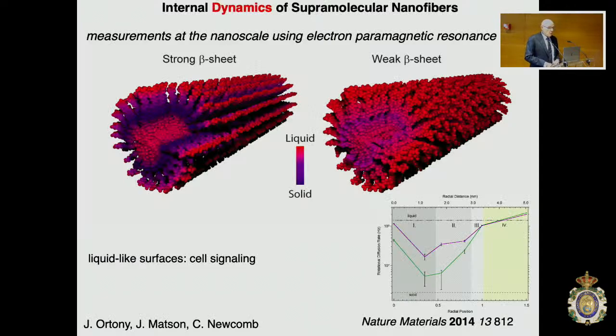From a dynamic point of view, this is an interesting slide. You are looking now at a dynamic map. So you see red color and blue color. And over on the left-hand side, you see that it is red on the outside where those signals are. And that means that on the surface, these structures behave like a liquid. And we actually measured this by a technique called electron paramagnetic resonance. And we found that the motion of the red part is comparable to a liquid in the nature of the motion. As you go down 1 nanometer or 2 nanometers into the core of the filament, it turns blue because there it is a solid.